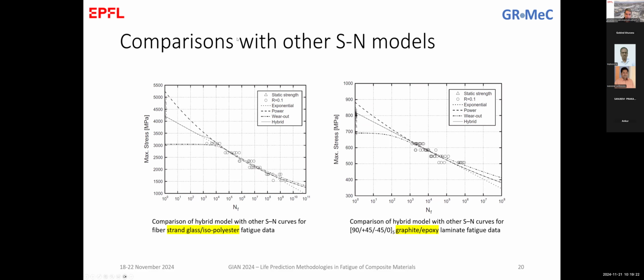The same here for strands. So a data set that contained also data up to 10 to the power of 9 cycles. And this happened because these strands can be loaded at very high frequencies. They are strands of glass and polyester, so they are not fabrics and they are not getting hot when you test them. So you can reach very high frequencies for the testing. And for a typical graphite epoxy, so CFRP material, again, we see that with our model, we can start with good prediction or good modeling. It's not prediction yet. Good modeling of the static strength data, and then follow and switch after a certain point to follow also this asymptotic behavior of the materials when we go to the high cycle fatigue.